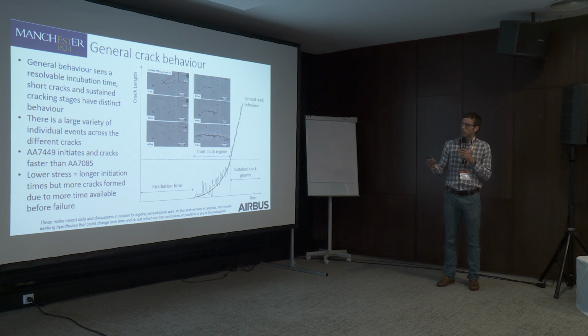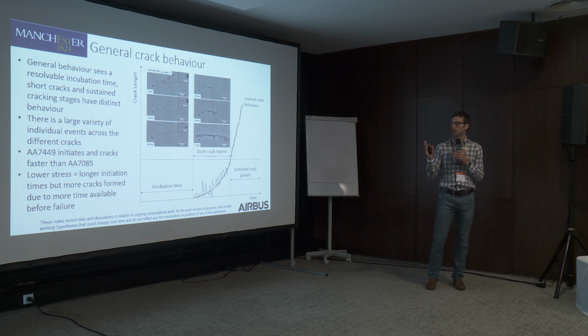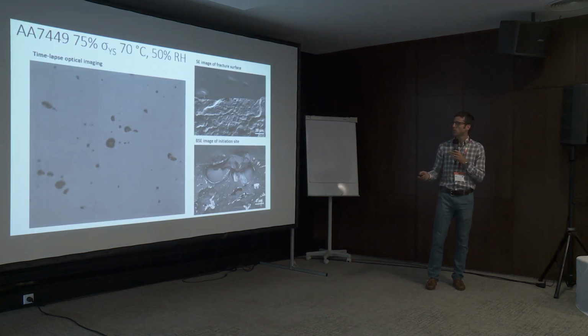It's worth noting, we've seen that for all of the tests under different conditions that we've done, 7449 is much faster to incubate and is faster to crack. But actually, when we test at the absolute stress levels that are the same, we see similar behavior between the 2 alloys.